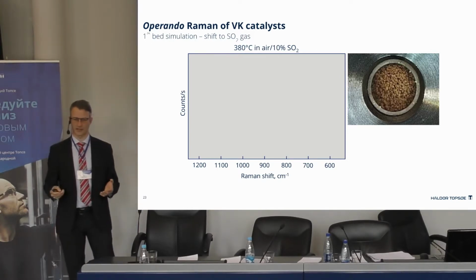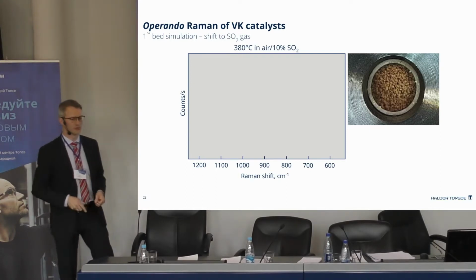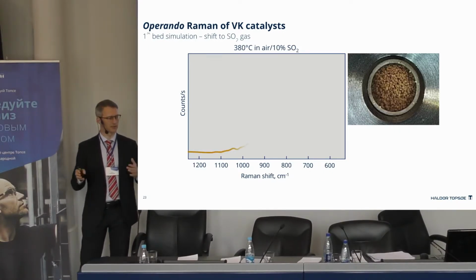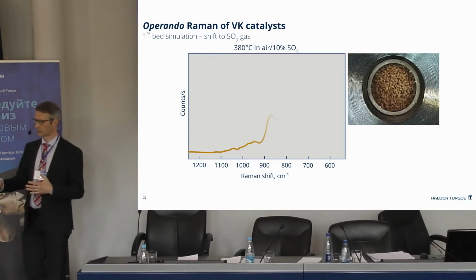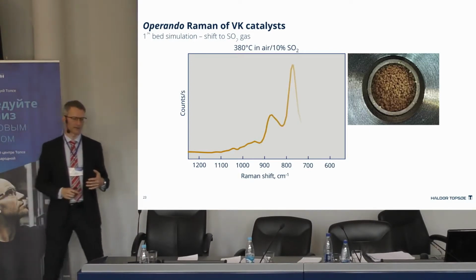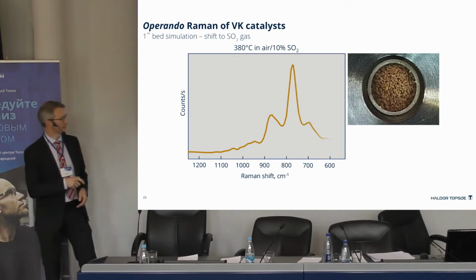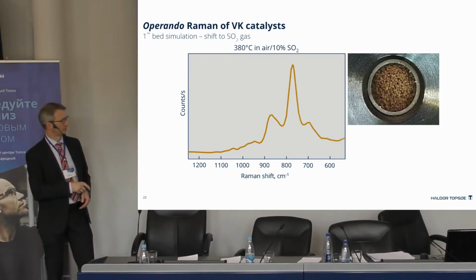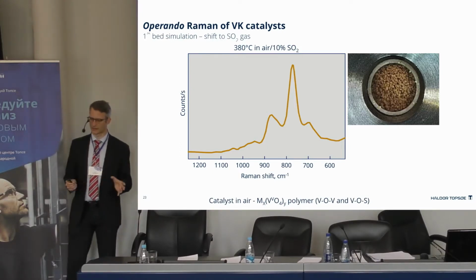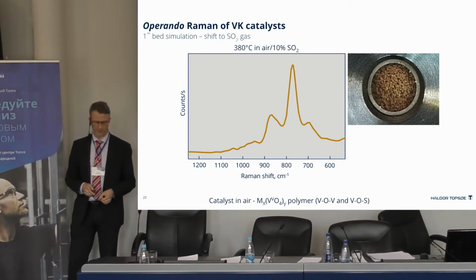Here's an example where we are simulating the startup of a first bed containing VK38 catalyst. You can see that's looking into the fluid bed here. First we look at the Raman spectrum for the catalyst in air at 380 degrees, typically a condition before process gas is introduced. And the peaks can be identified as vanadium 5 dimers and polymers in the catalyst, and it's also the yellow color.